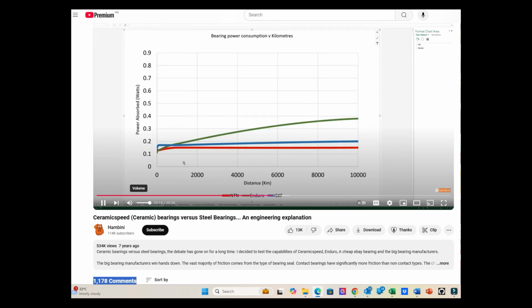If we go to this next slide, which is the bearing life, this is effectively the bedding in period of the bearing, and the red and the blue are NTN and SKF respectively. The red line is an NTN bearing which has a steel cage. The SKF bearing has a TN9 cage. Both, the power absorbed doesn't really increase much over kilometers, whereas the power absorbed by the Enduro bearing increases significantly. And that is due to the hard ceramic balls basically wearing the raceway away.